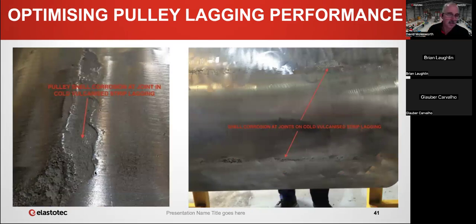When you do get joints opening up, corrosion of the surface, this is commonly what you see when you're refurbishing a cold bond pulley. You get these lines of pitting. This is along the joins between the strips. One area where it can become a real problem is if the pitting in the shell is deep enough that you reduce the shell thickness below the design minimum. It means that the shell would need to be scrapped in those circumstances.